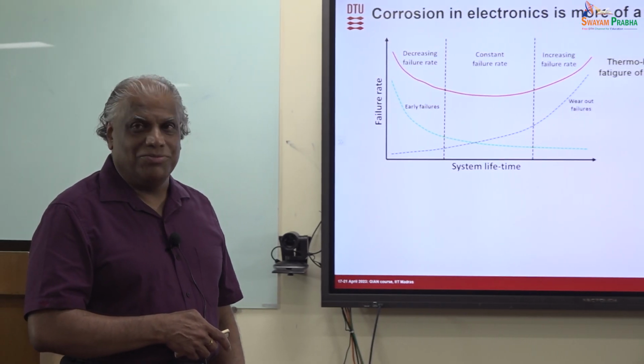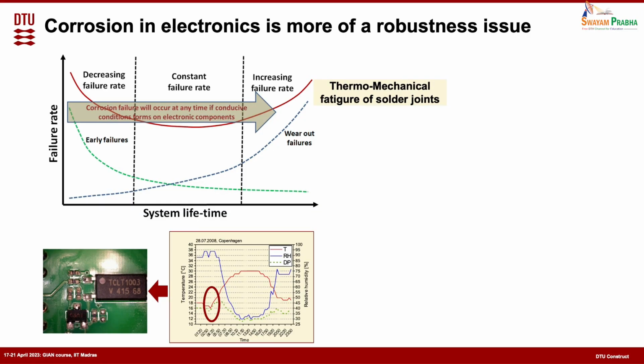This is exactly the issue. Corrosion failure will not fit into that because corrosion failure is not an aging failure. Corrosion failure will happen when a conducive condition is forming on the PCB surface. There is a condensation on the PCB surface. The transition to failure is very, very fast. The only thing is that you need to have condensation happening on the PCB surface, and then from this point to this point it will take only 15 minutes or 30 minutes. That's all the time period. So as long as you can have condensation existing on a PCB surface for 30 minutes, you can get failures.